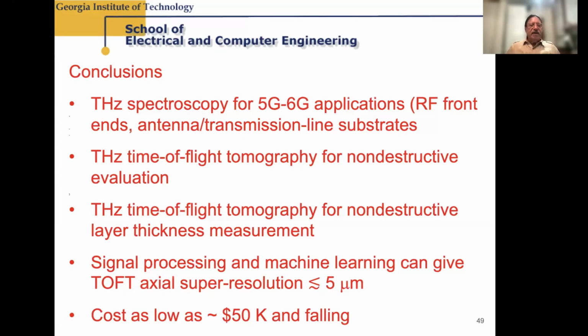We spent a lot of time on Terahertz time-of-flight tomography for non-destructive evaluation, so to find defects, to characterize the thickness of layers. Again, the signal processing and machine learning is the key to getting useful information here. It can give axial super resolution down to and even less than, in some cases, 5 microns, despite the fact that the actual optical resolution physically is longer given the wavelengths involved in our useful band.